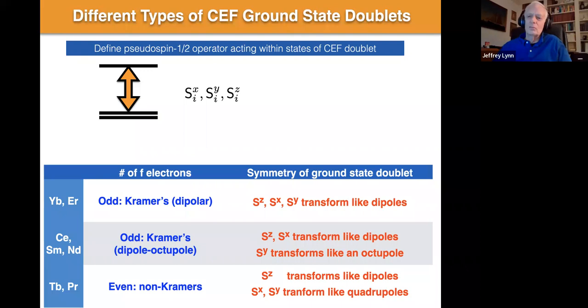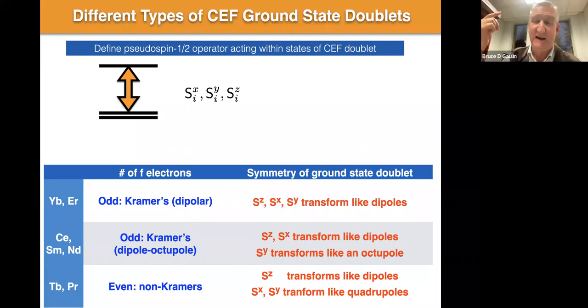You could measure this in cerium zirconate, at least, by doing a powder X-ray diffraction measurement after you synthesize the material, and you just leave it on the diffractometer for like a week, and you'll see the peaks shift in angle. There's an easily measurable d-spacing change as you acquire more and more cerium 4+ in the system. Now you can go back, you can reduce the material. So this is cerium zirconate oxidizing in just atmospheric oxygen in the air, and if you anneal the system in a reducing atmosphere, like say hydrogen or carbon monoxide, you can get rid of much of the cerium 4+.